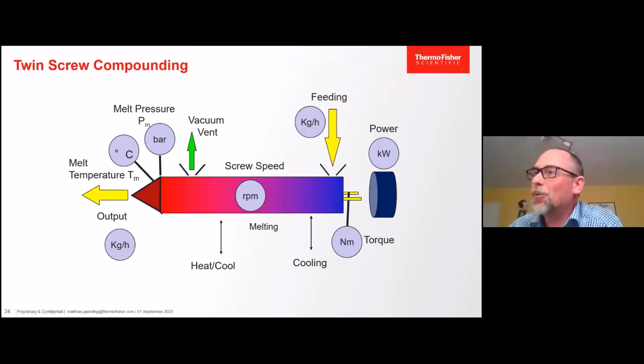So we have a motor with its power in kilowatts. We can measure the torque either by a torque sensor with a Polylab system, for example, or by the motor power, calculating the Newton meters we apply to the screw shafts. We have the feeding in kilograms per hour, cooling. We have a screw speed, RPM. We are melting the material. We need to heat or cool the extruder barrel, and eventually we will take out some gas, some vapors, by a vacuum venting. We can measure the melt pressure, the melt temperature, and of course the output of the process.